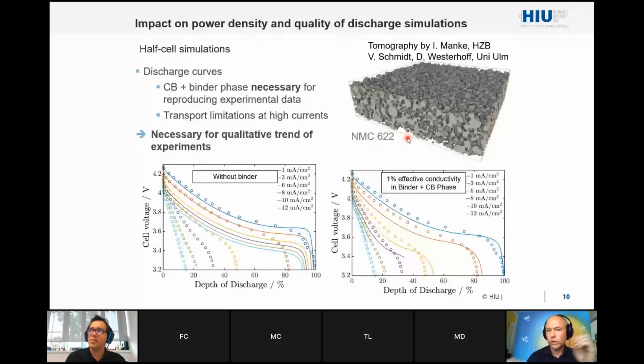And what was even more interesting to see is that if we wanted to predict the capacity fade, these are really thick electrodes, and we tried to do the simulation without the binder, then our simulations, which are the closed lines, have been far away from the real results. I mean, you could fit for small currents, but if you increase the currents by a factor of 10, we were far off the observed measurements.